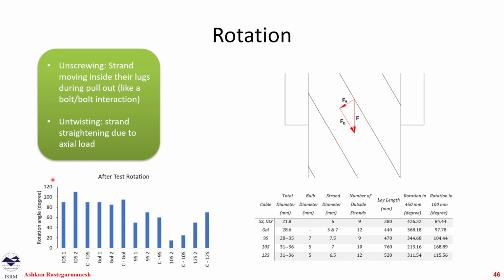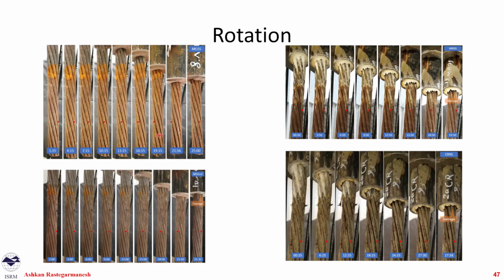So in order to measure this better, during our small scale test, we put a camera, and in the bottom section, you see the time of the test, and we see the type of the cable that we test on the top. We put a point here. These are the red points that you see here. We follow this point during the time of the test. So in the beginning, this point was here. As you can see, this point is moving.